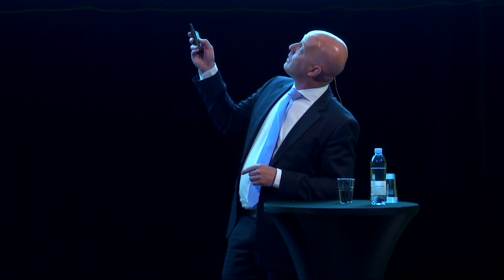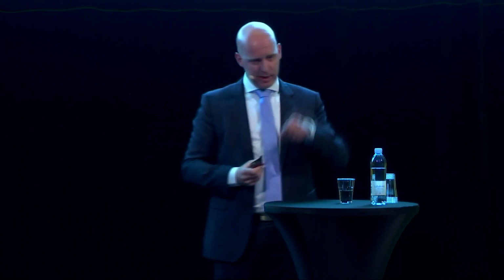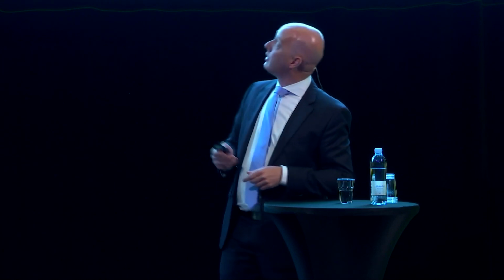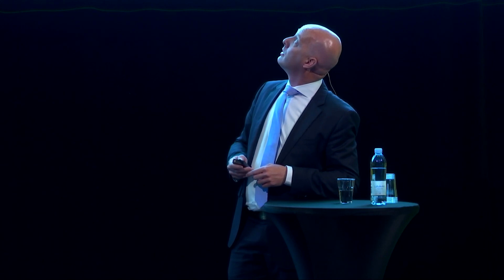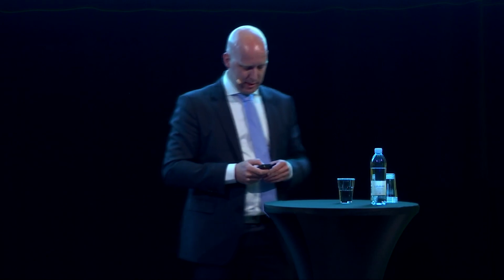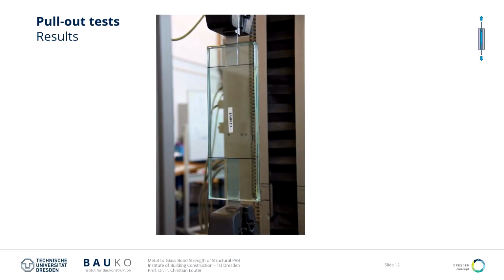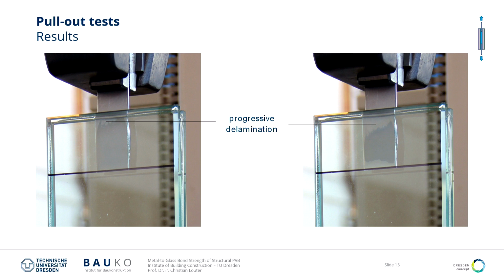And you will see delamination starts from the top there. So the metal is getting a little bit thinner, let's say, by pulling it. And then you see the delamination starting at the top and progressing downwards, until we reach the full capacity of the specimen, and then the metal is pulled out of the laminate. You can see that again. So delamination starts there because of the necking of the metal and also the deformation of the interlayer. And then this is close to being fully pulled out.